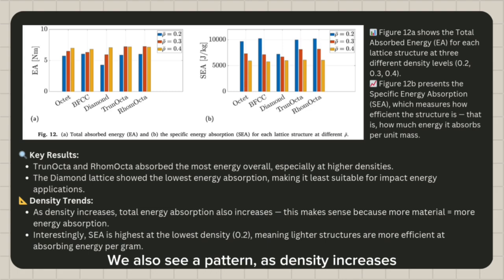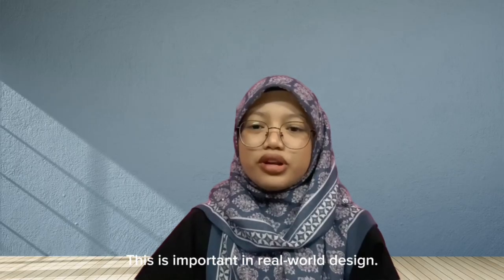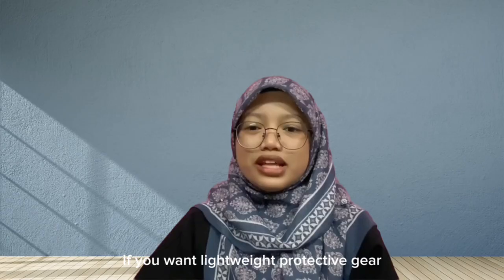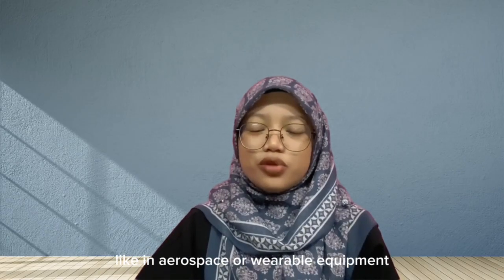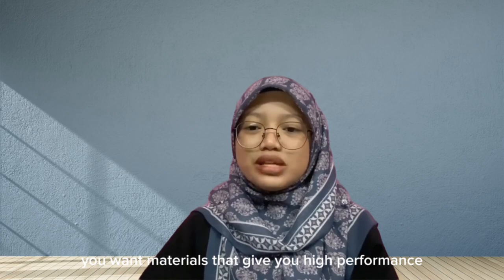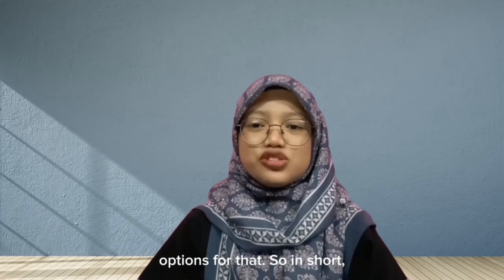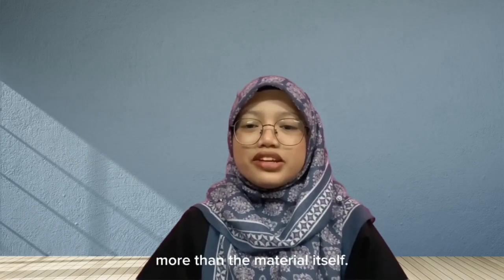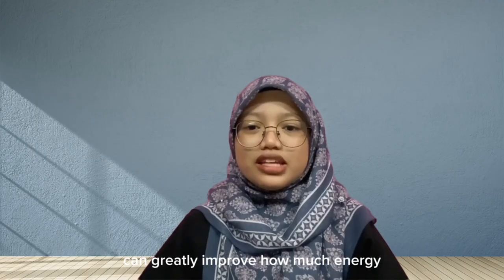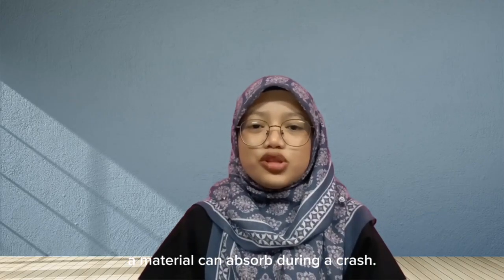We also see a pattern. As density increases, the total energy absorption goes up, which makes sense because there's more material to absorb the force. But interestingly, the SEA is highest at the lowest density, 0.2, meaning these structures are most efficient when they are light. This is important in real-world design. If you want lightweight protective gear, like in aerospace or wearable equipment, you want materials that give you high performance with low weight. TrunOcta and RhomOcta are clearly the best options for that. So in short, the shape of the lattice matters more than the material itself. Choosing the right geometry can greatly improve how much energy a material can absorb during a crash.